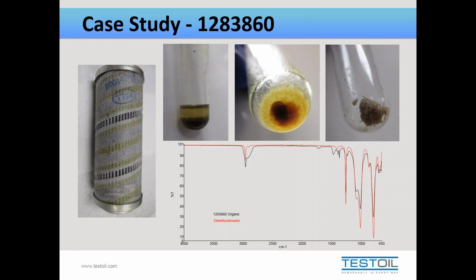But what was interesting is that we did find silicone, which indicated that there might have been a two-phase system going on, because the silicone oil, potentially grease, would not be expected to be compatible with the ethylene glycol lubricant. And incompatible fluids are known to form patchy deposits that can behave similar to varnish. So we suspected that they had a two-phase system, a layer of silicone, a layer of the ethylene glycol, that probably impaired the proper pump operation.